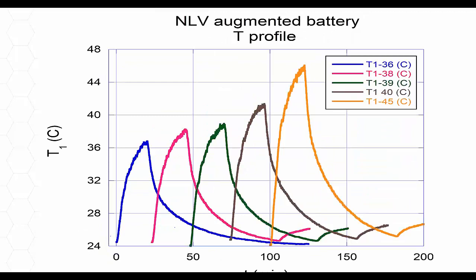And also this is the temperature profile during the augmented battery testing. You can see 36, we are at 36 degrees C. When we went to 38, 39, 40, you can see that at 40 ampere hours, we were about 41, 42 degrees C. And then when we went to 45 ampere hours, the temperature of the cell did not exceed 46 degrees C. So we are still on the safe side of the battery.